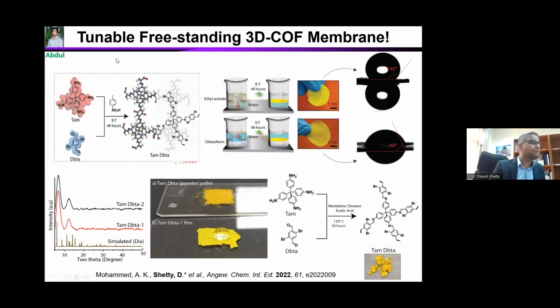Then he went back to lab and he started using the 3D tetraamine linker building block, and a simple 2D linker. The chemistry is very simple. We are using a well-known dynamic covalent chemistry, imine condensation chemistry. And the one trick we played here is that we did the interfacial synthesis, liquid-liquid interfacial synthesis, which means we have two different immiscible layers. Obviously, the membrane forms in between these layers. But the change here is, in one case we use an ethyl acetate and water system. In the other case, we use a chloroform and water system. Same building blocks, please remember. Condition is same, room temperature.